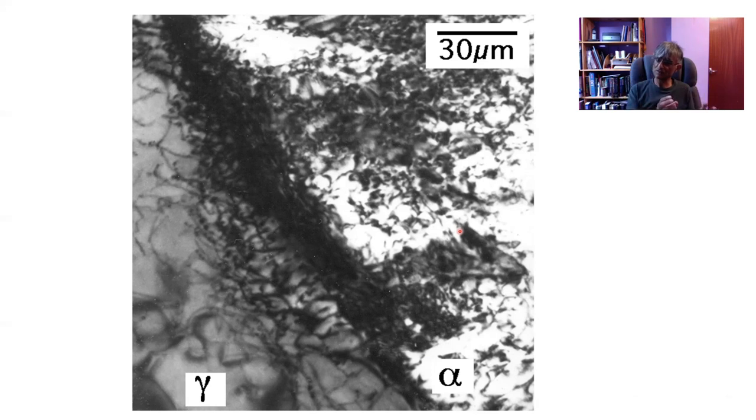These dislocations are directly a consequence of plastic relaxation in the austenite and subsequent growth of bainite into that region. But once you reach a critical value of the debris, the stress driving the interface, which comes from the chemical free energy change, can no longer overcome the pinning by the debris. So there are quantitative models to predict when this would happen and are consistent with experimental observations.